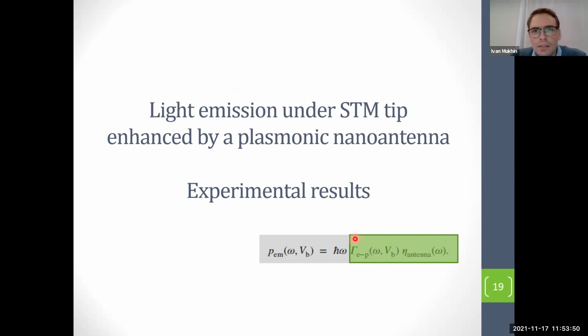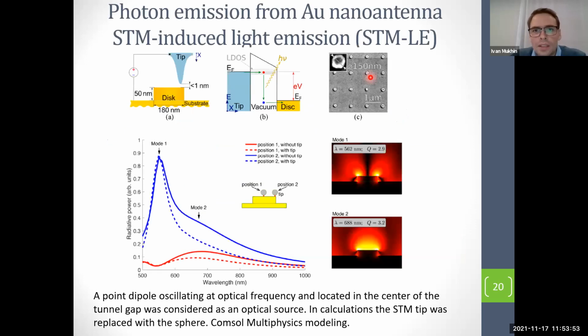So what we have done, we have fabricated an array of single gold nanodisks on the metal surface, and this is our experimental scheme. So a metal antenna in the shape of a gold nanodisk. This is our tip, and again, this is the energy diagram. So we suppose that IV curve study allows us to estimate the energy position of enhanced local density of optical states. First, we started with numerical calculation and considered different positions of an STM tip. This is the STM tip in the center of our disk and at the edge of our disk.